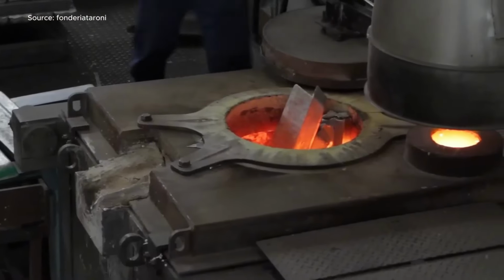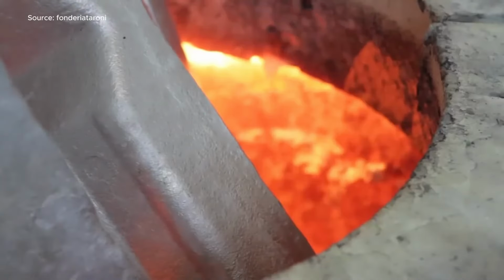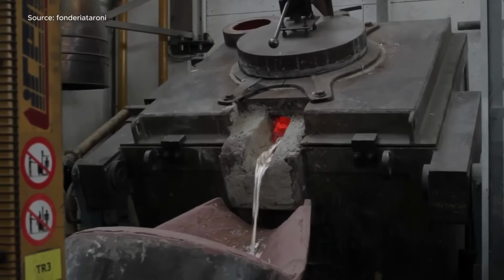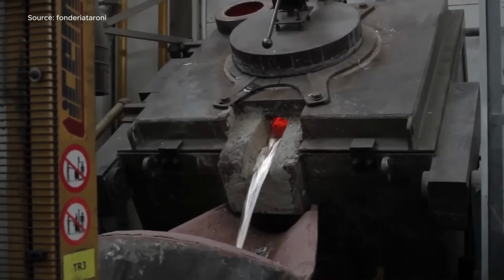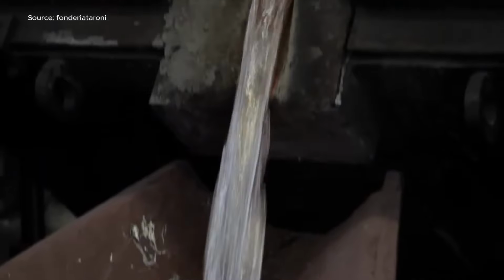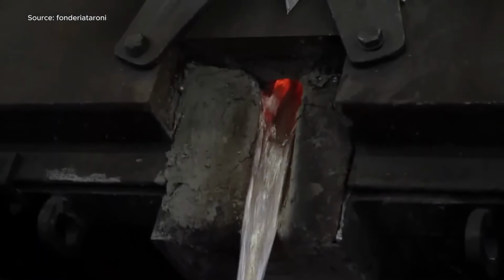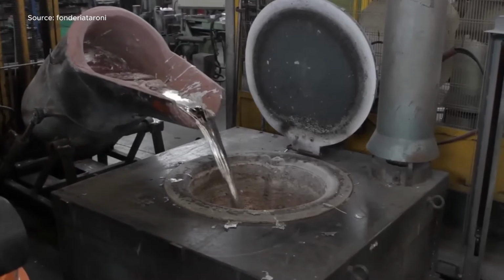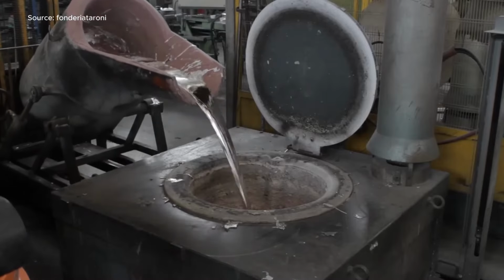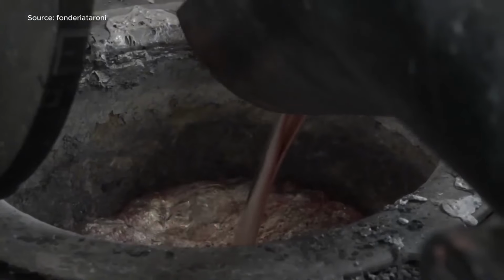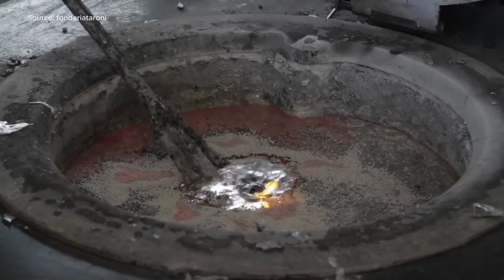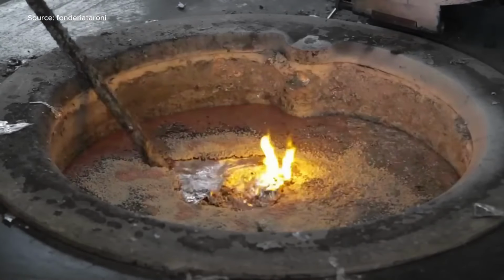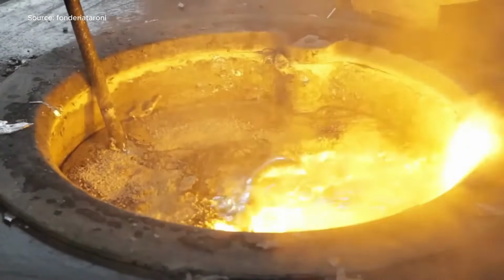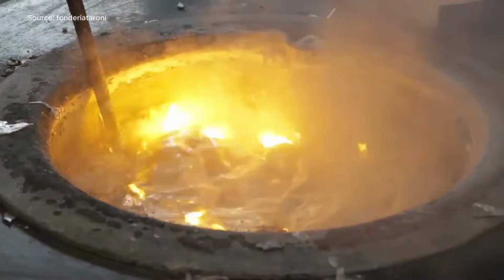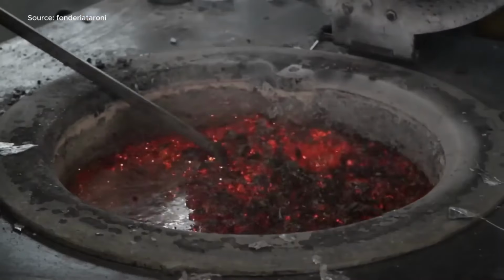Fonderia Taroni, located in Italy, specializes in aluminum gravity casting, focusing on precision and high-quality production. The process begins with melting aluminum ingots in induction furnaces at temperatures ranging from 720 degrees Celsius to 750 degrees Celsius. The molten metal is then poured into steel molds, each capable of holding up to 10 kilograms of aluminum, with cycle times of about 5 to 10 minutes per casting.